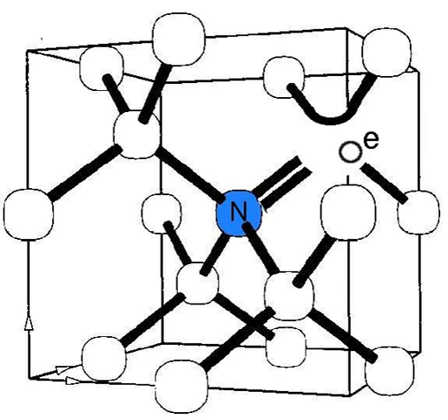This application relies on good compatibility of diamond nanoparticles with the living cells and on favorable properties of photoluminescence from the NV- centers: strong intensity, easy excitation and detection, temporal stability, etc. Compared with large single crystal diamonds, nanodiamonds are cheap, about $1 per gram, and available from various suppliers. NV- centers are produced in diamond powders with sub-micrometer particle size using the standard process of irradiation and annealing described above. Those nanodiamonds are introduced in a cell, and their luminescence is monitored using a standard fluorescence microscope.